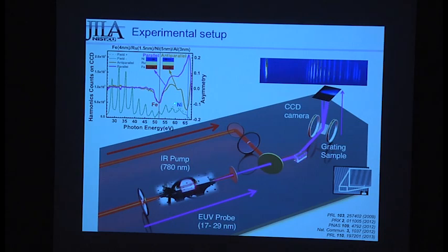What you measure is the asymmetry, which is the difference in the reflectivity for two different directions of the Helmholtz coil. So we could have magnetization in plane in two different directions. And then after you heat the material with the femtosecond laser, if there is quenching of the magnetization, the difference between these two curves goes to zero.